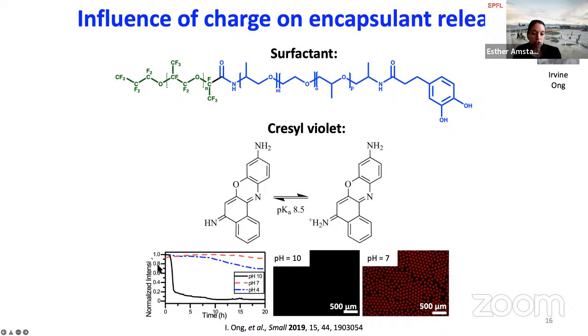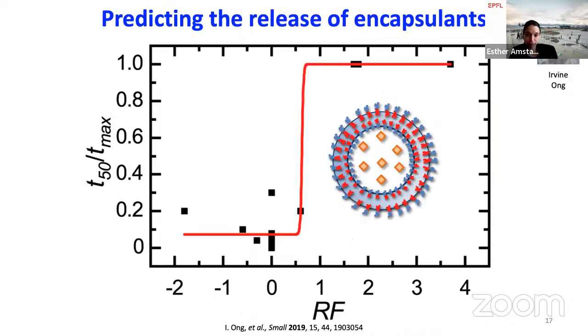Whereas if we lowered the pH such that the two molecules were neutral, you had nearly no transport again across the oil phase. And to me, that indicated that you get the transport when the surfactant and the encapsulant attract each other. And we showed through many more experiments that it's electrostatic or strong van der Waals interactions that must occur between the two types of molecules for the transport to occur quickly. But as soon as you have some repulsion between them, you have nearly no transport again throughout the shell.